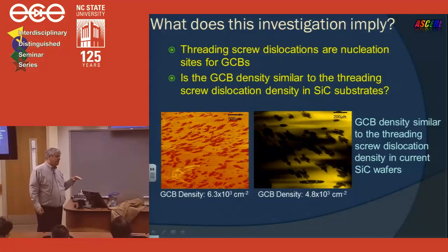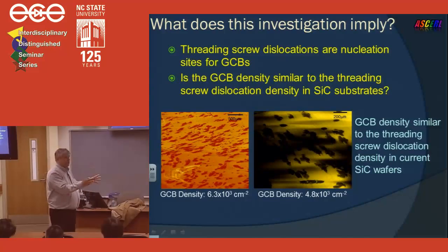And the graphene is going to be thick at the nucleation site, because it appears that the dislocation is a conduit for silicon sublimation, releasing a lot of carbon atoms, and that makes the graphene thicker. And then it spreads out, eventually covering the entire sample. And so that sort of explains why the first image that I showed you, the carbon face growth, looks so messy. It was so chaotic.